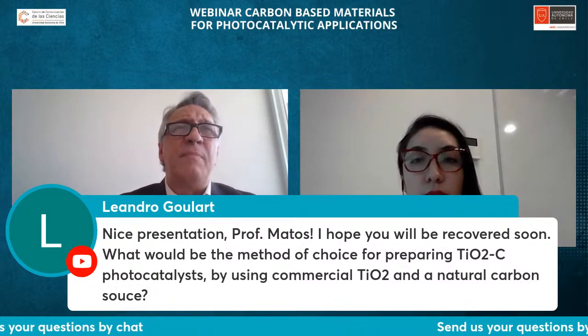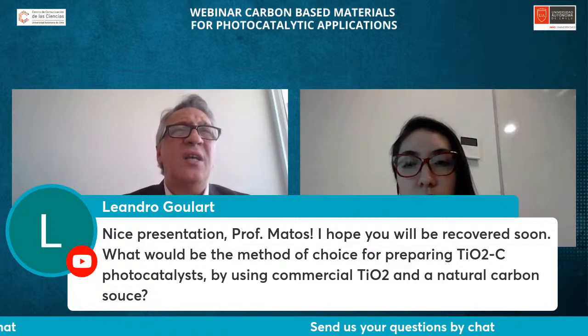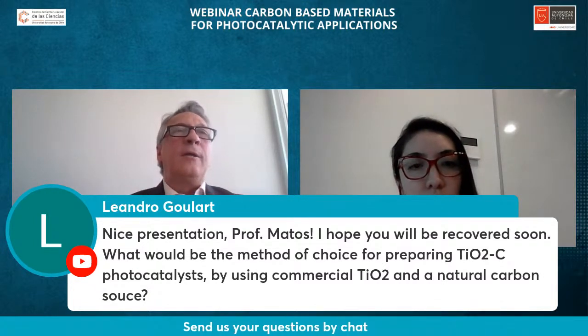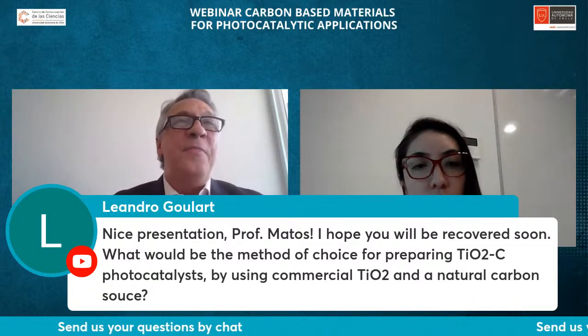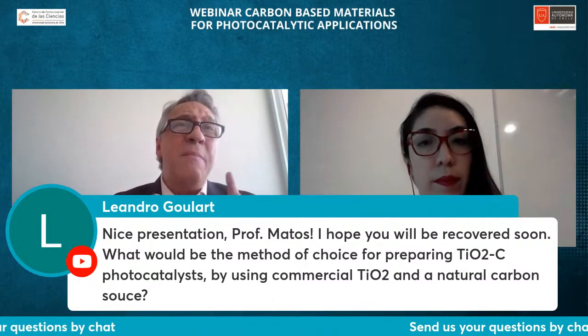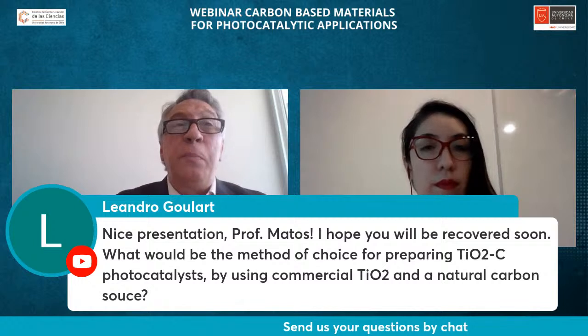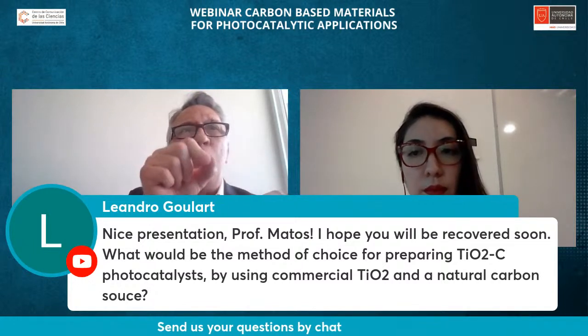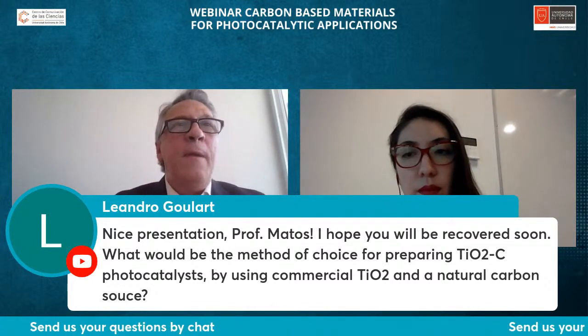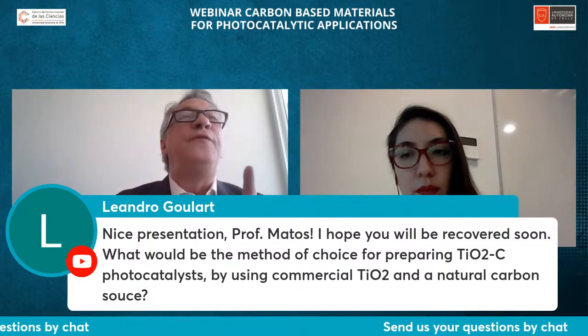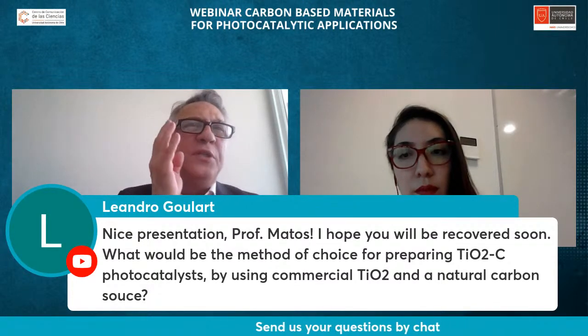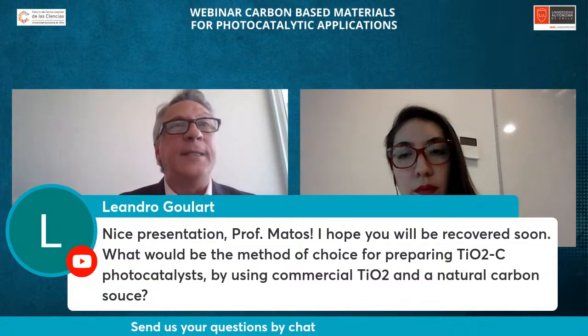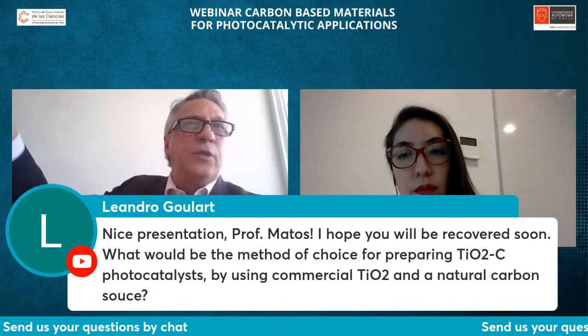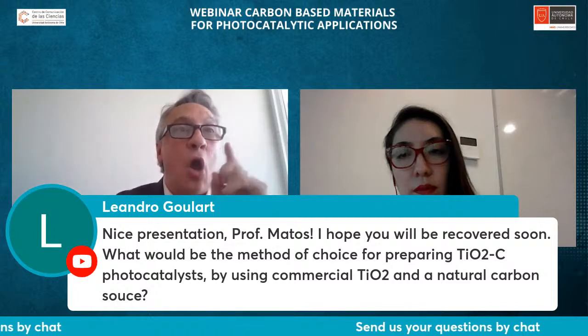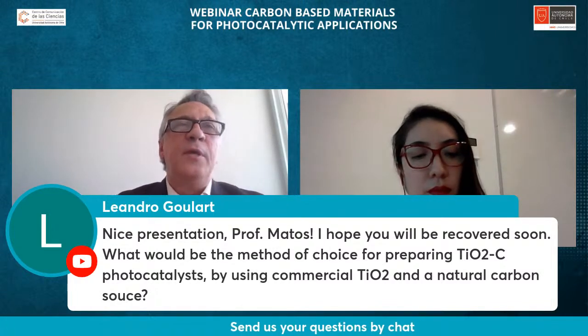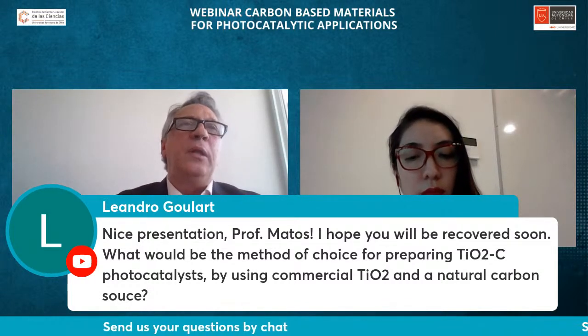We have published, for example, the synthesis of carbon quantum dots within the crystal structure of titanium dioxide and even zinc oxide by microwave assistance. We have also published, for example, titanium doped within the micropore structure of silica, by different ways. We have published it by thermal synthesis, using conventional autoclave reactors in thermal conditions, but also promoted by microwaves. So there are the two important possibilities.